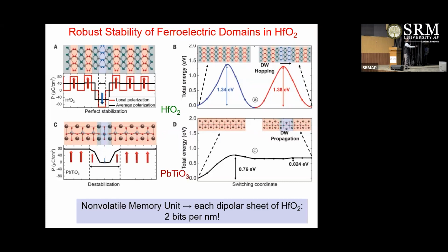And if you take another competing material called lead titanate, which is also a very fascinating technological material, it doesn't have this property, because if I try to switch only one unit cell of the crystal, it leads to the entire crystal switching to the opposite direction. So this hafnium oxide that we have predicted allows you to store binary information at sub-nanometer scale, half a nanometer scale.